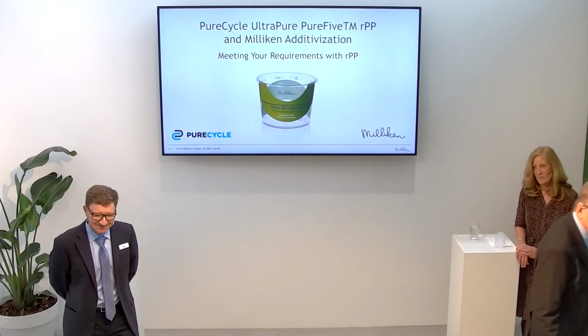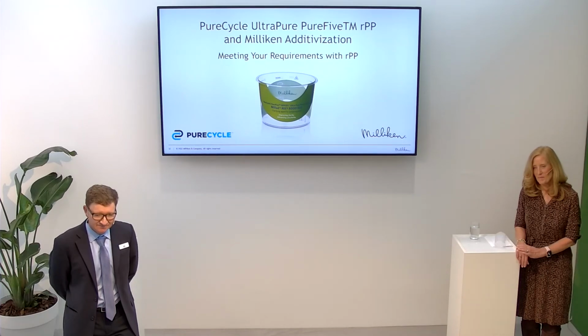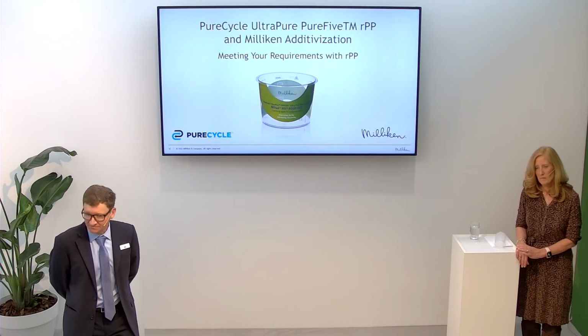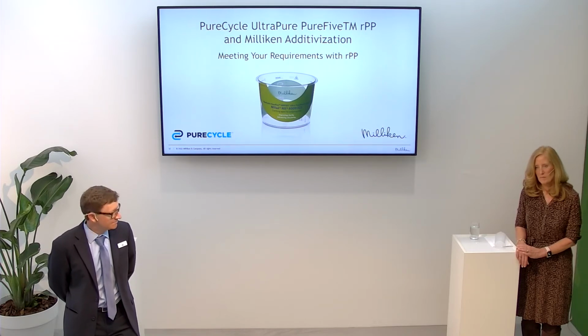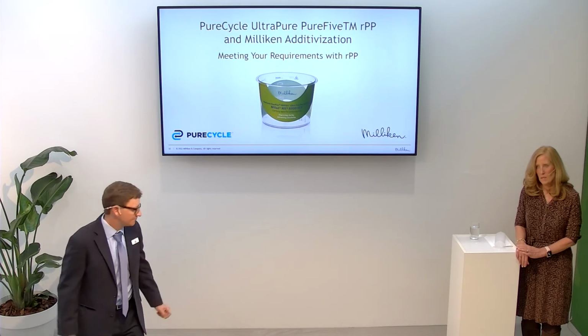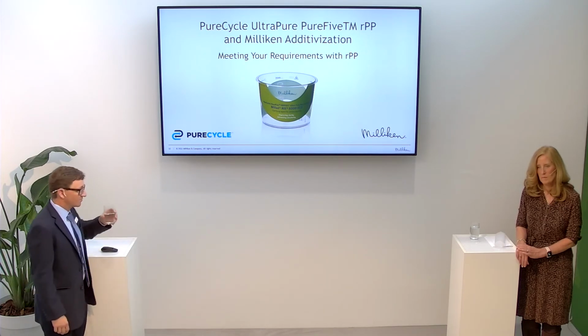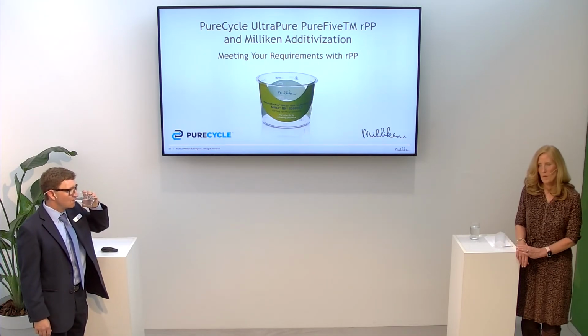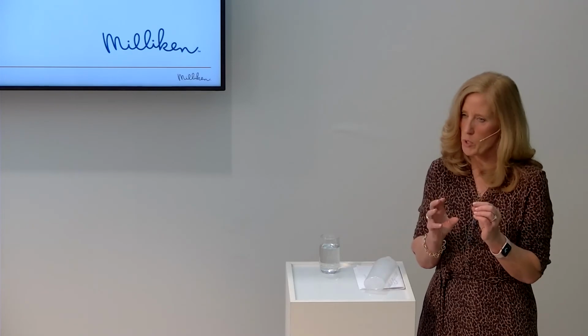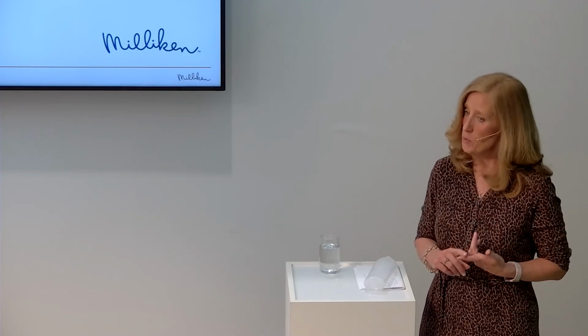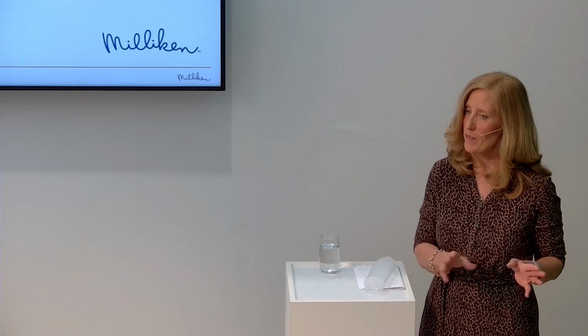Just to ask, in terms of your raw polypropylene input material that you get from stadiums and so on, do you find that your melt flow varies from batch to batch, depending on what polymer's been used? Is your raw polypropylene really a mixture of impacts, randoms, and whatever you can get? It is a whole mixture, and it has been consistently falling between a 10 and a 20 melt flow, really hovering between 12 and 15. Both on the stadium and on curbside, and they're very similar.